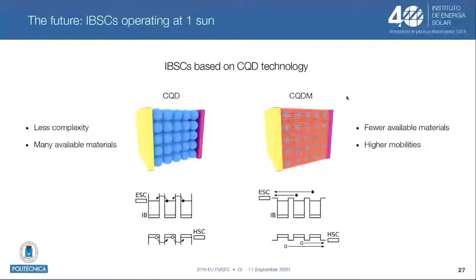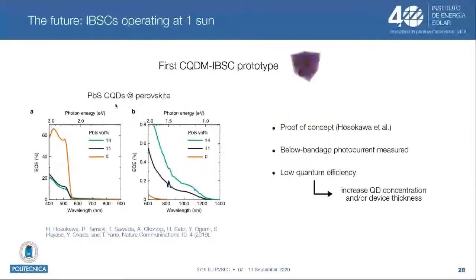So the last slide is just the proof of concept of this kind of materials. This is work by Hosokawa and co-workers, and they built the first IBSC made of colloidal quantum dots inside a perovskite matrix. They demonstrated photocurrent due to absorption in the perovskite and absorption in the quantum dots, although the photocurrent due to absorption in the quantum dot is still a bit weak. So this points to further research, maybe increasing the quantum dot concentration and or device thickness, but still it's a big step forward for this new approach.